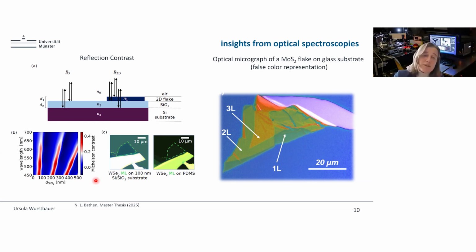So here we're using a substrate of silicon dioxide, which is very commonly used, and we change its thickness. And you see there are regions where we have a rather high contrast, sorry, it's the red ones, and the dark blue ones are regions where we have a weak contrast. So for instance, here, at 150 nanometers, the contrast is really poor.